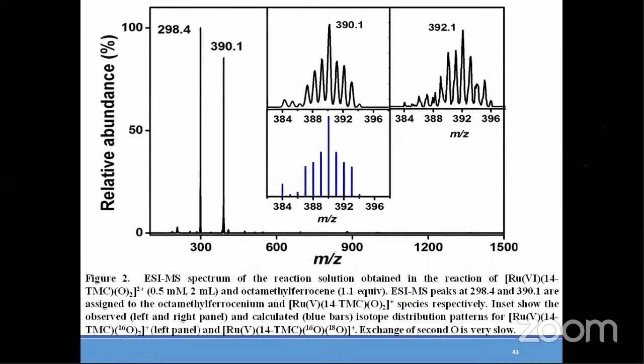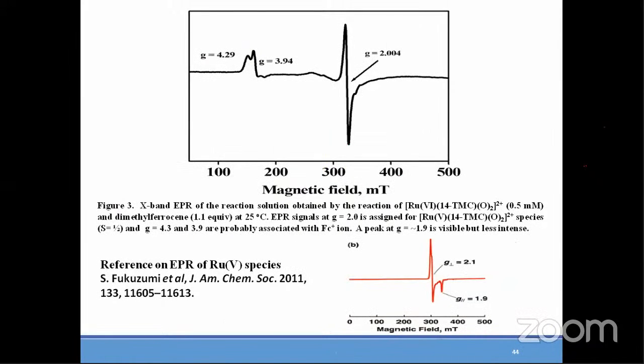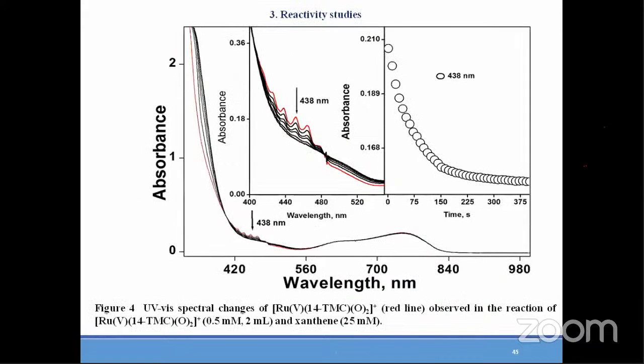You can see here the mass and everything was very clear, so there was no problem. We also characterized this compound by EPR. It was showing the ruthenium(V) oxo EPR character, which was similar to what was reported earlier. But some more work is to be done. It is not so clean, so I cannot at this moment say that it is 100% the V oxo species.